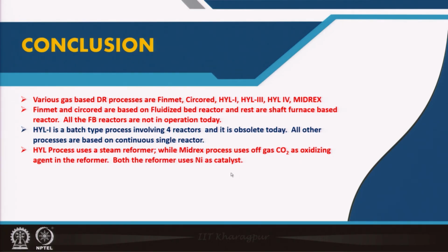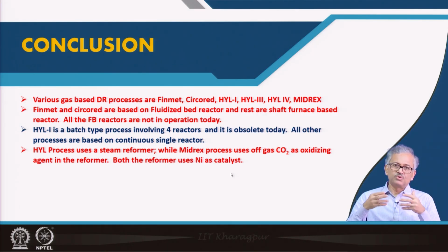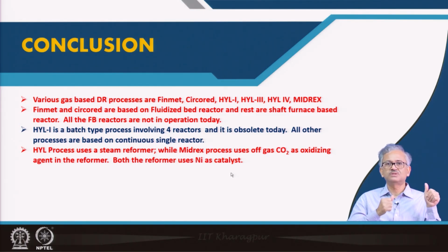Both reformers use nickel catalyst, but in the case of the midrex, one problem is there. In the reformer, the catalyst has to be replaced frequently, because the poisoning of the nickel catalyst with the off gas reforming is more. That is, the replacement of the nickel catalyst in the midrex reformer is more compared to the HYL reformer, because the HYL reformer is a steam reformer and does not involve any off gas. The midrex uses off gas, so in spite of cleaning, a lot of dust will be there, and that dust will poison the nickel catalyst.